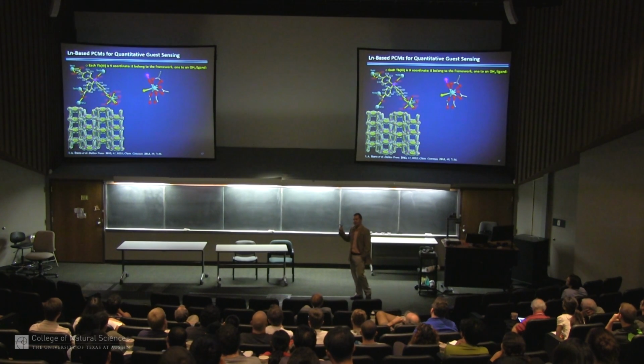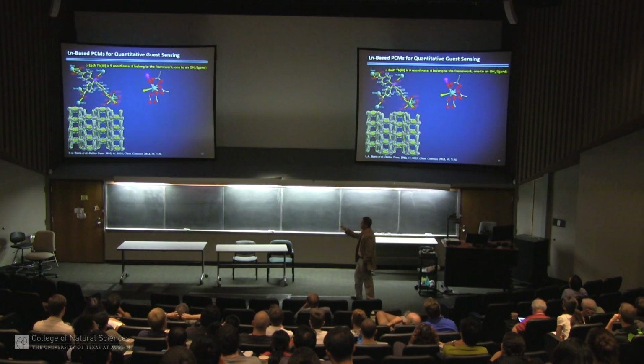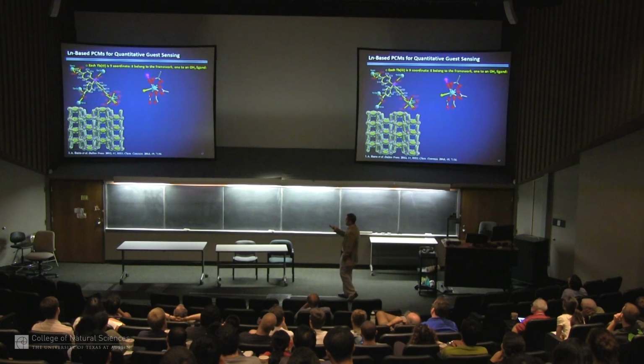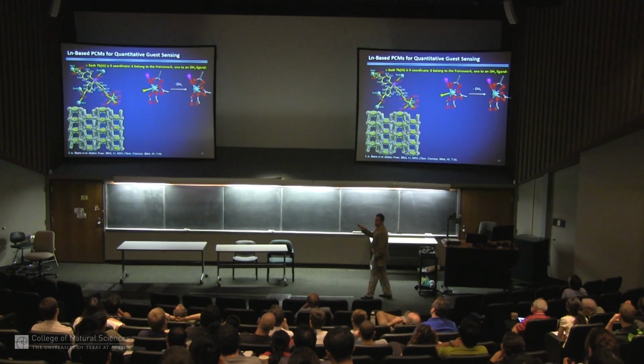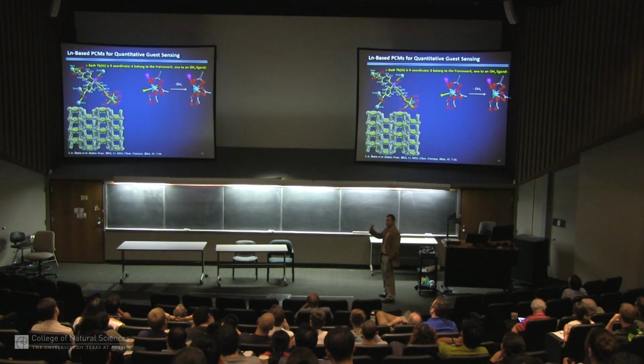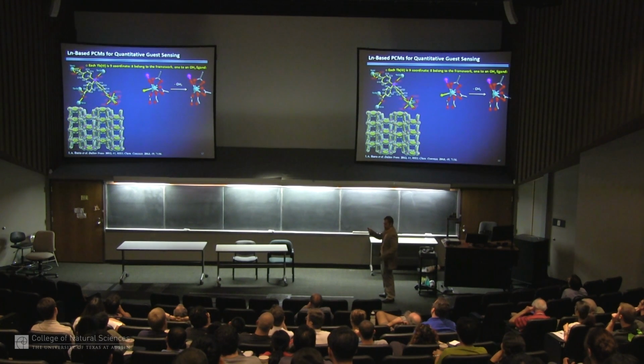That's good because if you can make anything in water, it's going to be stable in water, and that's an industrially important question. How stable is this in ambient air, in moisture, and so on? And there's really water in the framework. And moreover, we can pull that off under vacuum. And you can see in a single crystal fashion, and I'm going to show you some more of these. It's cool that you can take a single crystal, glue it onto the diffractometer, heat the crystal up and see something change without the crystallinity being lost. We see this water disappear, but you see the structure hasn't changed.